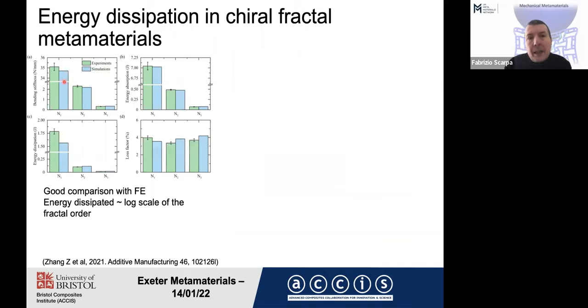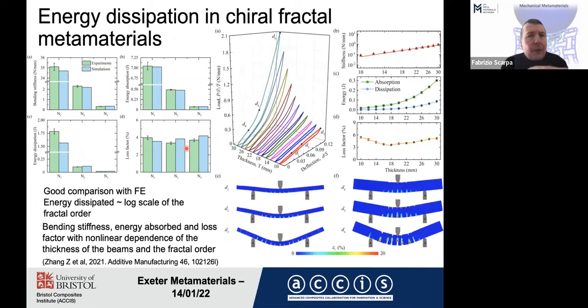And also in terms of energy dissipated, you can see that it follows this type of log scale of the fractal order that we have seen before. If you compute the loss factor, which is proportional to the ratio between the energy dissipated and the energy that you have inputted into the system, you will see that actually the loss factors tend to be quite constant with the fractal order. And this is also something that is quite interesting. We haven't seen this feature in this architecture, but we have also observed a similar feature in another type of fractal architecture. So something really yet to be explored, but quite interesting.